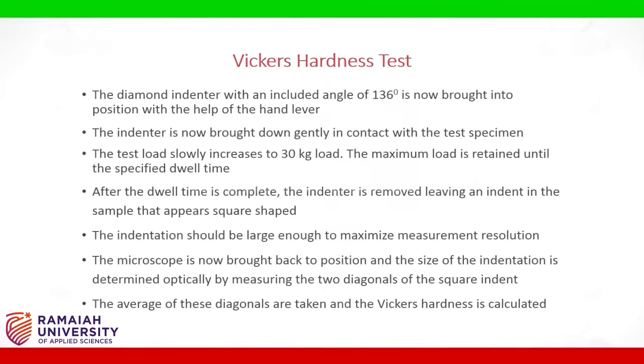The diamond indenter with an included angle of 136 degrees is now brought into position with the help of the hand lever. The indenter is now brought down gently in contact with the test specimen. The test load slowly increases to 30 kg load. The maximum load is retained until the specified dwell time. After the dwell time is complete, the indenter is removed, leaving an indent in the sample that appears square-shaped.